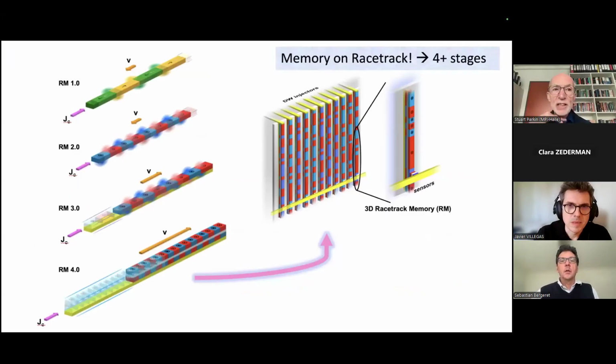So since 2002, the racetrack has evolved through four very distinct families of racetracks, as I like to call them. In racetrack 1.0, which is what we demonstrated in 2008, we used very soft magnetic materials, nickel iron and nickel cobalt alloys, in which we knew from the work from the 1930s and beyond that the current is highly spin polarized through spin-dependent scattering. And we could show that the domain walls would move at speeds of about 100 meters per second without significant heating of the racetrack. At higher current densities, you start to nucleate domains due to temperature effects.